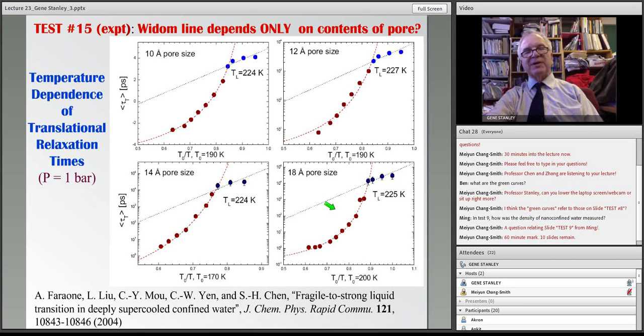If this was a function of the pore size, then we could say indeed the pores make a difference. But notice that the same fragile to strong occurs with the same crossover temperature, 225, for a wide range of pore sizes: 10 angstroms, 12 angstroms, 14 angstroms, and 18 angstroms. So for me, this is one of the best refutations of the stubborn idea that confined water is just totally different than bulk water. This is an absurd statement. It's different in some ways, but it doesn't mean it's totally different.